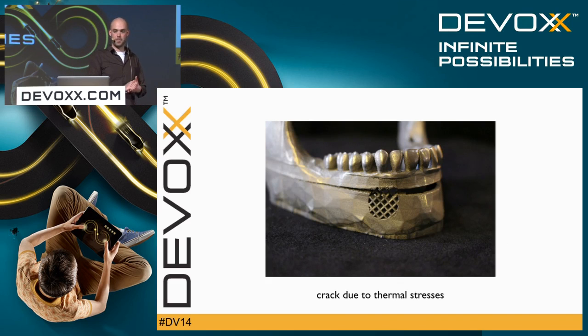This is an image of a jaw with a huge crack inside of it. Now, the awkward thing is that the crack appears 3 weeks after it was being built. We built it, put it in a demo closet, and then after some while, 3 weeks, there was a huge crack in it. Well, that's actually due to thermal stresses.